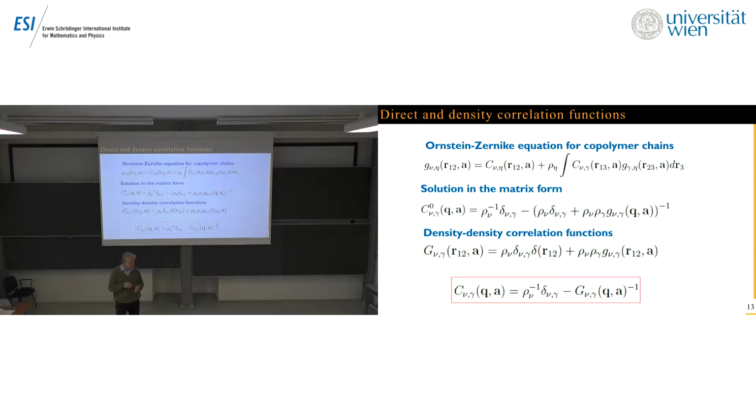And then to check that, we have used these direct correlation functions just in the theory of coil-coil diblock copolymers, which is well developed, in order to obtain the first few terms of the expansion obtained by Leibler. So the quadratic term, of course, should be correct, and it is indeed exactly the same.